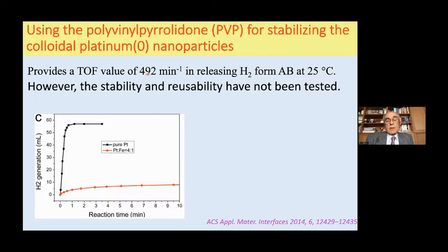it's active. The platinum nanoparticle is active. However, the activity is less than that of bare colloidal platinum nanoparticles. So instead of 600, they observe 492 because the stabilizing agent covers the surface and the activity is lowered. And as I said, the stability and reusability have not been tested, unfortunately, in that study.